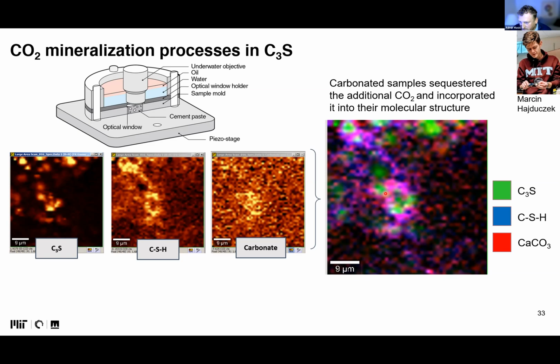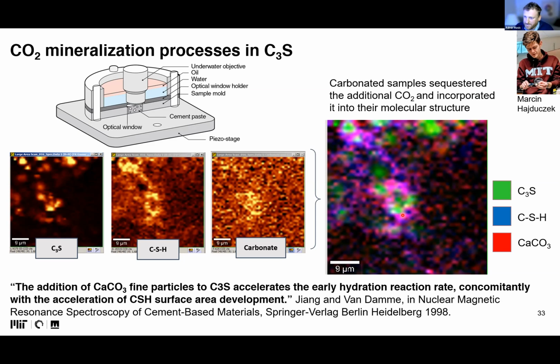Are there nanoparticles that perhaps will start seeding CSH? Probably it's what is happening, because my disorder, the calcium hydroxide and eventually calcium carbonate, if the CO2 is present, might be of the nanoscale. That's a good guess, because the broadening is also often due to the surface deformation of nanoscopic features, and so there is a lot of work here to be done.